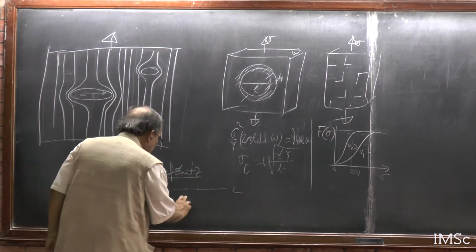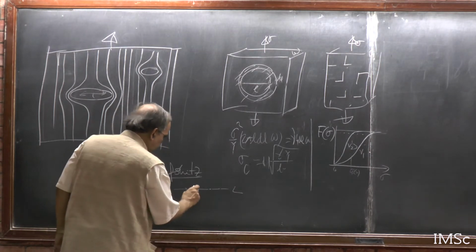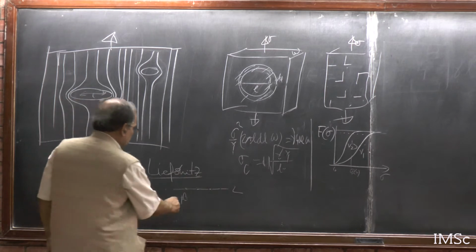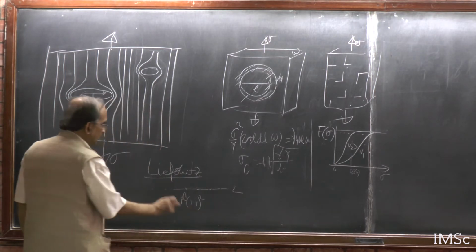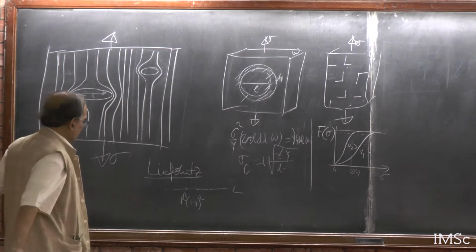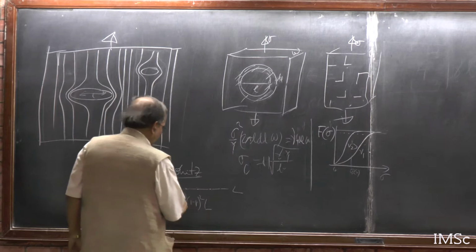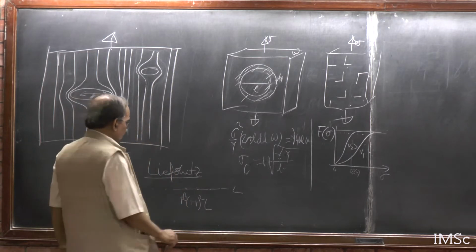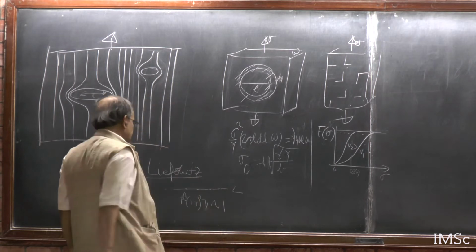But if you want to get L successive defects, then it will be P to the L, and then on both sides there should be the original bonds. So the probability of a defect of size L is this multiplied by the volume, and when that goes to 1, it means you have a defect of size L.